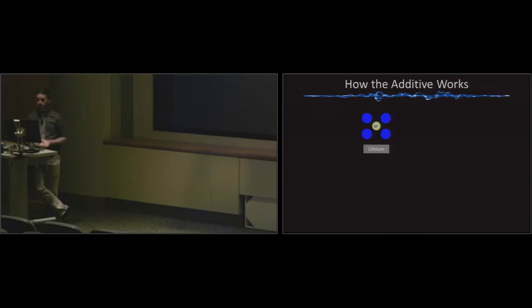So how does this additive work? In a typical system, your lithium ion will have about 4 solvent molecules kind of attached to it. And when you bring 2 of those to the surface of the lithium, they're going to react and form this red material called lithium ethylene dicarbonate. So I have it colored in red because red is bad. And so this material is porous, and that's why I'm showing these holes here. It's also insulating. So the lithium will only be able to deposit on the surface through those holes. And what ends up happening when you do that is you get these dendrites growing. And so that's what causes the dendrites.